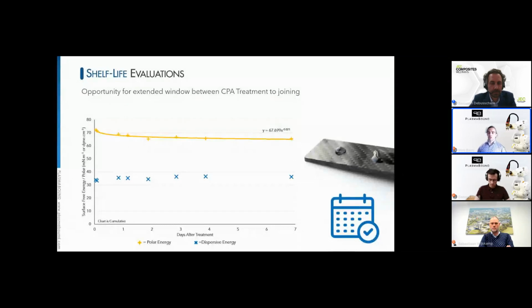This is contrary to other preparation techniques, which may last only hours, some maybe half a day. So this means that essentially you can treat the part and store it. And we did not put this in any special environment anywhere around. It was simply sitting on a shelf, taken down, tested, and put back up. So this provides an opportunity for an extended window between treatment and bonding.